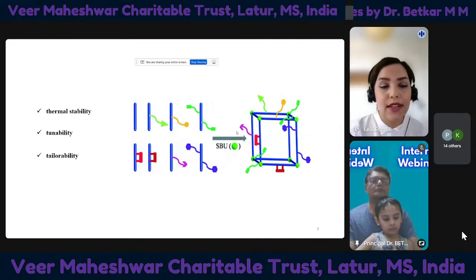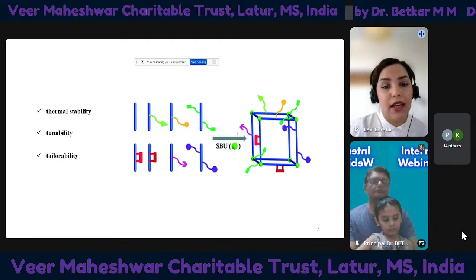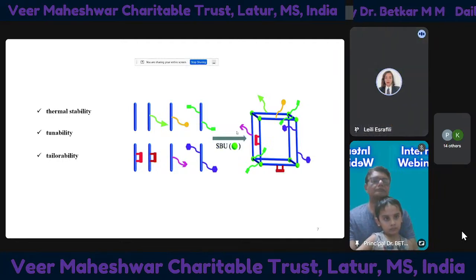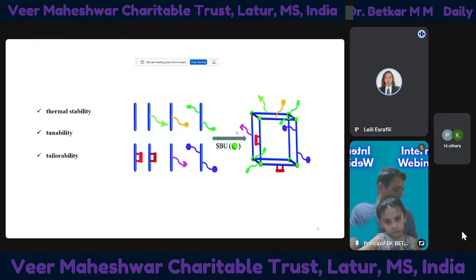You can increase the length of the linker, and by not changing the rest of the functional groups on the MOF, especially the metal, you can increase the surface area, or you can add different functionality in the linker. As you can see here, these are a series of isoreticular MOFs, or IRMOFs. They have the same topology, but the only difference is they have different surface area because their linkers are different. They have adjustable topology, as I said, and also different chemical tailorability, and this can happen via synthesis and after synthesis via post-synthetic modifications.